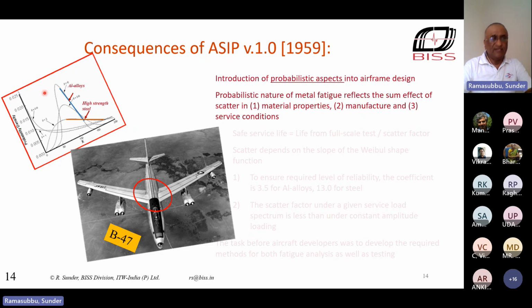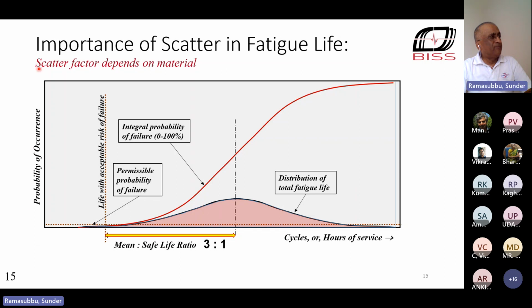To explain this further, let's just look at this probability of occurrence of fatigue failure against hours of service of an aircraft. So if that is the distribution scatter that you get by testing several aircraft, the ratio is about 3 to 1. You have to take a 3 sigma deviation from the mean and tell the user that, for sufficient protection of safety of flight, he cannot use the aircraft beyond this point. He has to discard the aircraft somewhere over here. That is the integral probability of failure integrated from this plot. So you can just imagine what is the price we pay if we use the scattered fatigue life to assign a safe service life.